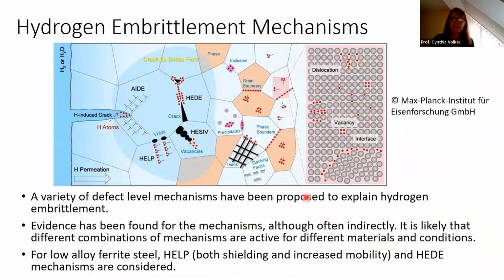I've tried to show you some of the mechanisms here using this very nice schematic from the Max Planck Institute for Iron Research. If we look over here on the right side, this is the microscopic or the atomic length scale. And here the red dots are supposed to indicate hydrogen. What they're trying to show here is that the hydrogen does in fact interact with all kinds of defects, interfaces, dislocations, and vacancies. And then we see the microstructural scale further to the left, showing segregation of the hydrogen again. And then all the way on the left, where there's a hydrogen-induced crack at the surface of the material, they show you schematically some of the mechanisms that have been discussed involving interactions of the hydrogen with various features of the microstructure.